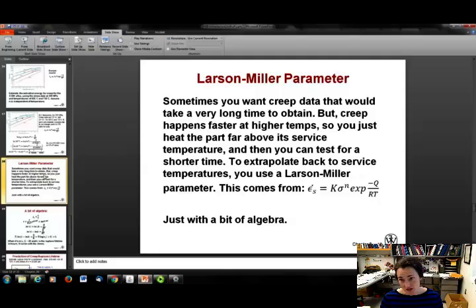Now sometimes you want creep data, but it would take a really super long time to obtain because the life of the part, you expect it to be years, for example. But you know that creep happens faster at higher temperatures. So if you want to do a test and you want it to take a reasonable amount of time, maybe you heat the part up to a temperature far above the temperature you would expect it to have in service, and then you can extrapolate back for the temperatures that it would actually encounter in service and figure it out that way. So you just do the test at a higher temperature and then figure out what would happen at a normal temperature. So we can use what are called Larson-Miller parameters and Larson-Miller plots to figure this out.